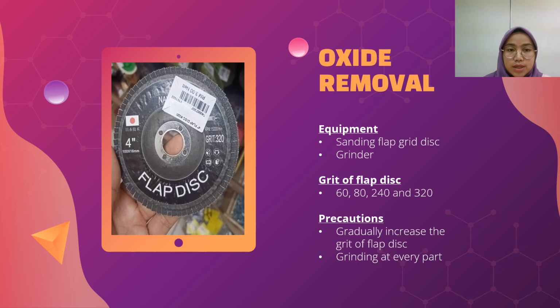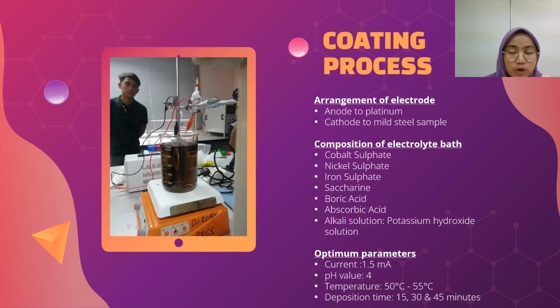The next process is oxide removal. Equipment used are sanding flap grit discs and a grinder. The grits of flap discs used are 60, 80, 240, and 320. For this process, the grit of the flap discs will be increased gradually and grinding must be performed at every part to ensure uniform removal of the oxide layer. Then we proceed with the coating process.